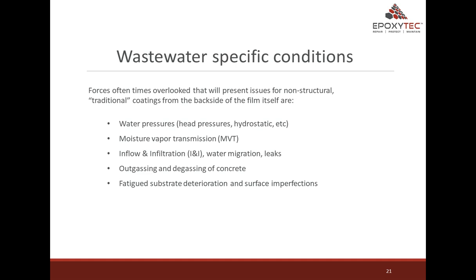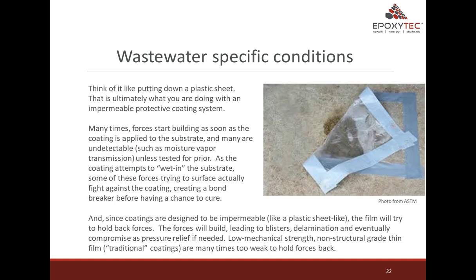Forces oftentimes overlooked that will present issues on non-structural traditional coatings from the backside of the film itself are water pressure, i.e. head pressure, hydrostatic, moisture vapor transfer, MVT, inflow and infiltration, I&I, water migration and leaks, outgassing and degassing of concrete, and fatigue, substrate deterioration and surface imperfections.